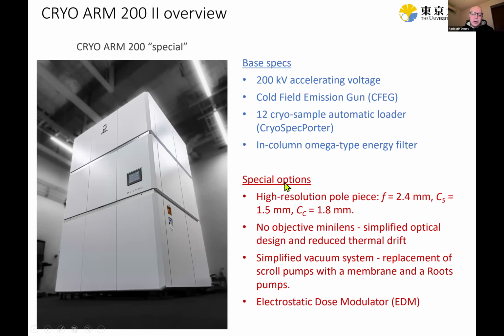And then we requested a high resolution objective lens pole piece. It has a narrow gap and also lower spherical and chromatic aberrations as shown here. So the standard values are 2.7 for the spherical and 2.8 for the chromatic. So you see these are lower values, so better optical performance. We also asked JEOL to remove the objective mini lens. This is a lens which they traditionally had in the bore of the objective lens and was used for low magnification observation, but it caused a lot of thermal drift. So switching between low mag and high mag caused a lot of drift.